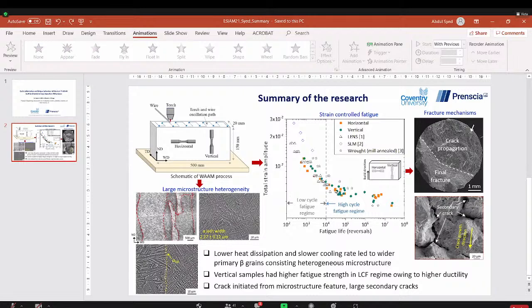However, we are parallelly conducting further studies, doing some in situ DIC and some neutron diffraction studies to understand the strain localization on these horizontal samples along the prior beta grain boundary, and then we could actually assess what is the real culprit for the lower fatigue performance of horizontal samples. Yeah, thank you for your response.